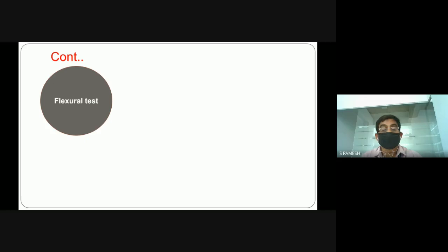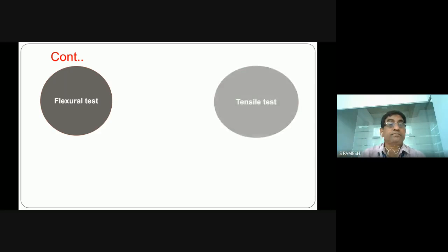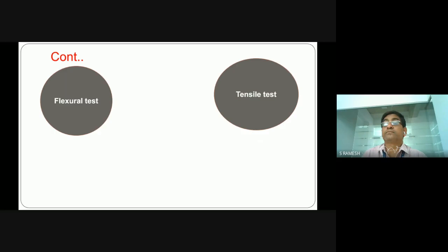And then the flexural strength. In flexural strength, as per the ASTM standard D790, we prepared a specimen of length into breadth into thickness of 125 into 12.5 into 3 mm. We used a gauge length of 100 mm and applied a load cell of nearly 10 kilonewton. The rate of loading is approximately 5 mm per minute. We did it.